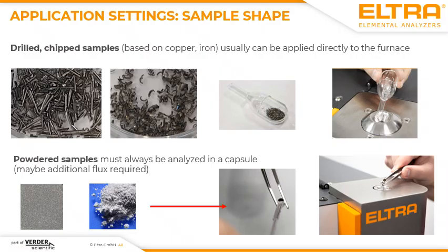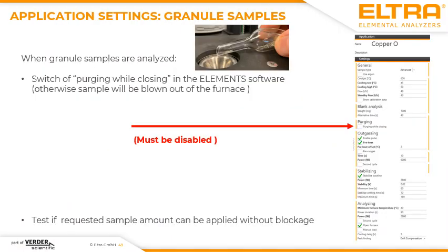When you have powdered samples, for example, metal powder or maybe ceramic-based powder, you always have to apply this powder in a nickel capsule, because it's not possible to apply powder directly, otherwise it would just stick inside the furnace and would not fall into the crucible. When granule samples are analyzed, you have to go to your application, which is defined in the application window of the Element software, and then you have to switch off the setting purging while closing. Because when you switch off the setting, no additional gas stream is applied to the furnace, so that all of the sample stays inside the furnace and is not blown out.